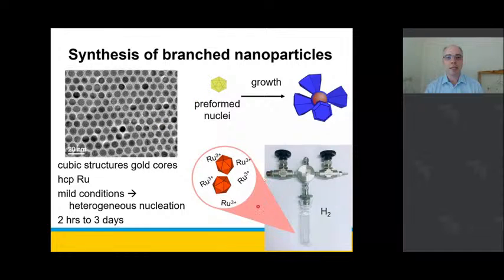So what we do to make these branched ruthenium particles, we make up a batch of gold seeds. We put them into a Fisher Porter bottle. So we have a solution of our gold nanoparticles and our ruthenium precursor. We put them into a Fisher Porter bottle. A Fisher Porter bottle is just one of these glass bottles. And then we fill the bottle with 1 atmosphere of hydrogen gas.